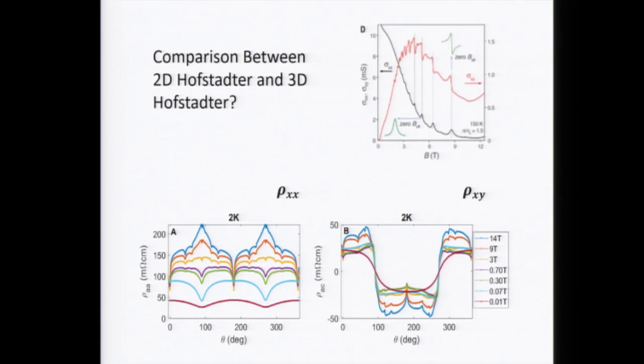So let's quickly go back to this transport signature. We see a resistance dip, corresponding to a conductance peak, whenever we hit the commensurate angle. This is very similar to the case in graphene. And for the Hall effect, we also see something roughly similar, but it needs to be resolved better.